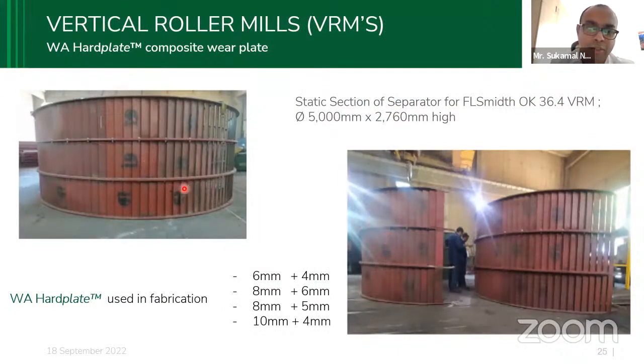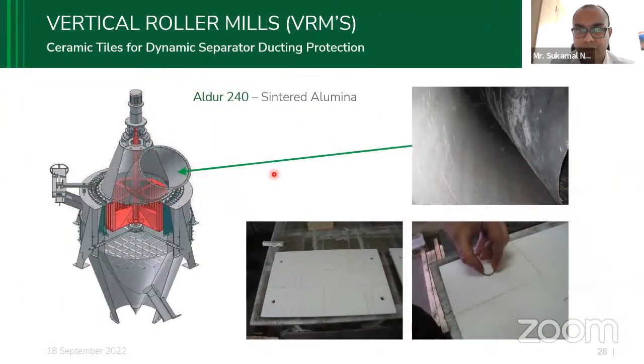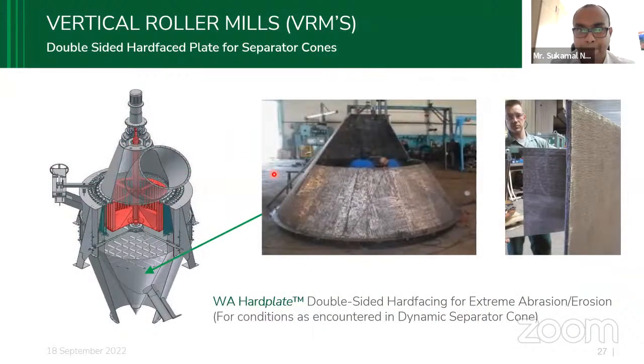So these are all used basically as hard plate. It enhances the life of these plates. Okay, it's a similar thing. It's called a separator cone. Because of the very high abrasion, the separator cones got eroded. So what we do, inside and outside, we use a lot of hard facing to protect or enhance the life of these components.